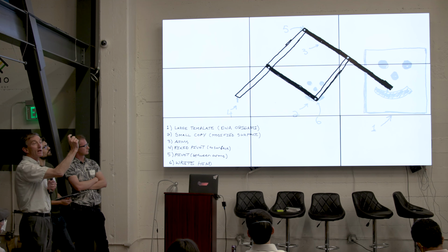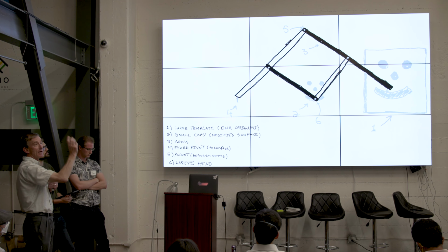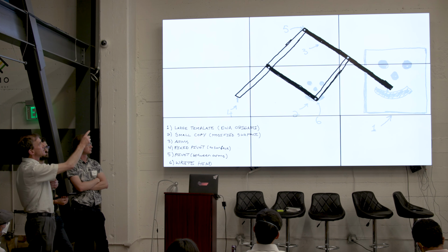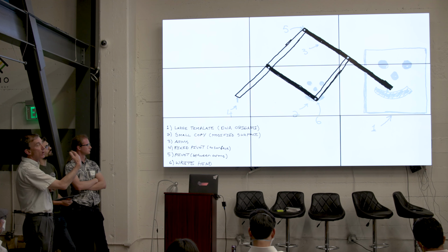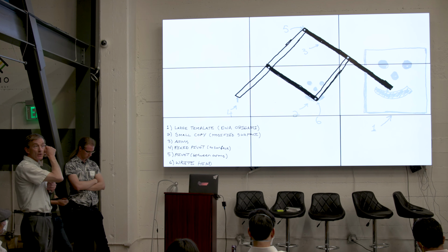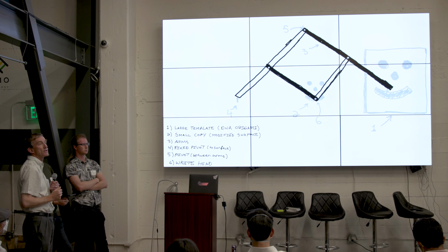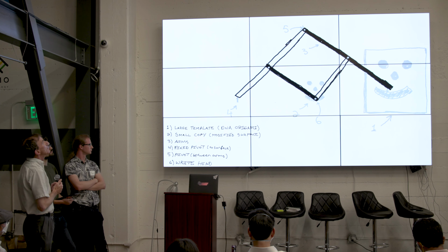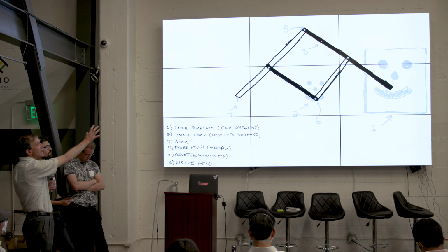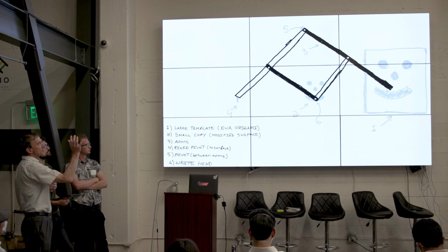So you position the white rods, if you like, on the top of this structure. You position the black rods on the bottom. You bind them to your DNA template. Within that, you've got a bifunctionalized short strand of DNA, for example, which has thiols on both ends, or dithiols on both ends, which binds to both rods and makes the hinge. And then, if you want, you can get rid of that sacrificial DNA nanostructure and leave yourself just with the functional elements that you need, the hinges, or you can leave it there because it's not doing any harm. Okay, so the project is to make that pantograph, to strap it to a surface.